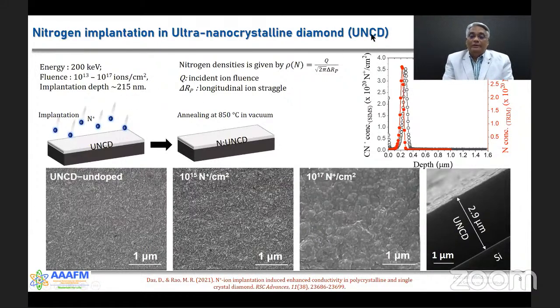We have grown extremely good quality ultra nanocrystalline diamond films, and then bombarded them, implanted them with nitrogen and phosphorus ions, and you can see the systematic change in the microstructure from the undoped one to higher doped or implanted nitrogen ions from 10¹³ to 10¹⁷ ions per centimeter square.